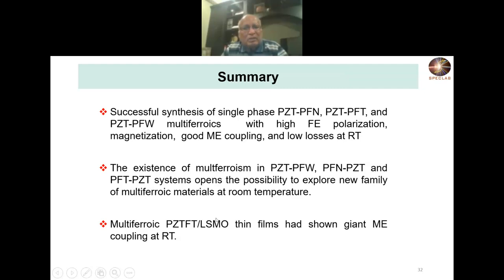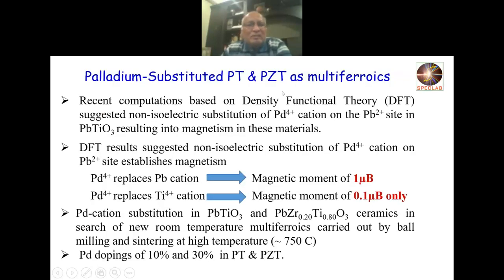But what I would show you now is another series of materials that we have recently started working on, which is palladium substituted lead titanate or lead zirconate titanate ceramics, multiferroics. See, this PT and PZT are only ferroelectrics. They are not multiferroic by themselves. Now, we are substituting with palladium, which is non-magnetic, but we expect magnetism occurring in this material. This was done theoretically in recent computational density functional theory. They suggested that Pd4+ cations can substitute at the Pb site, that is the A site.